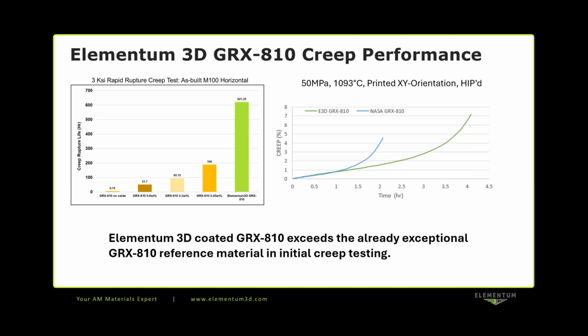On the right is a creep life curve that Elementum 3D did with an external test lab. We printed both of these materials, reference material and our coated material, and again are finding that our creep life is meeting or even exceeding NASA's already great performance.